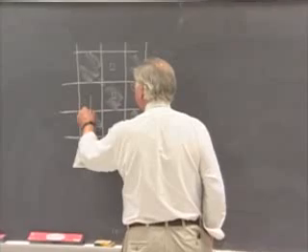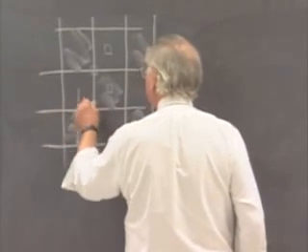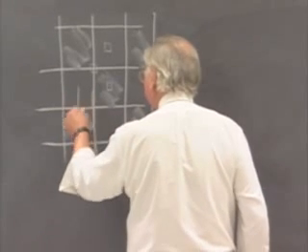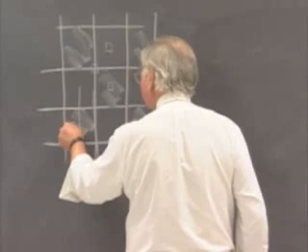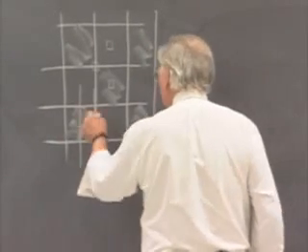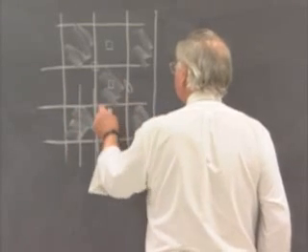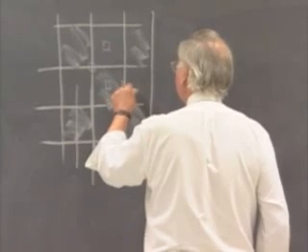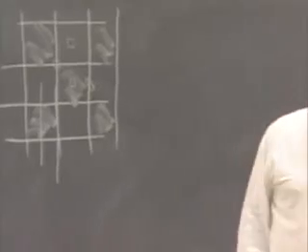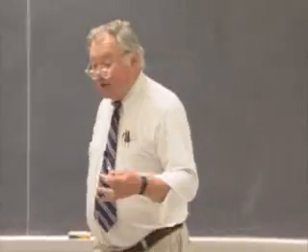Similarly, there are mirror lines like this that are true mirror lines. The pattern is left invariant. There's another locus, such as this one here, where when you reflect, you go from a black one to a white one and then back to a black one when you do the operation twice. So there are black-white mirror planes as well as regular mirror planes. There are 2-fold axes, but all of the 2-fold axes are black-white axes. White to black, black back to white. So that's a new sort of transformation that we can develop if we wanted to, switching the color.